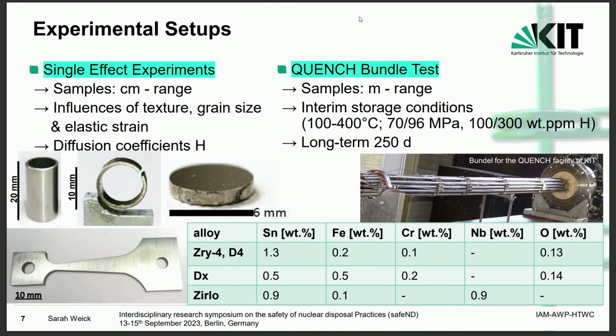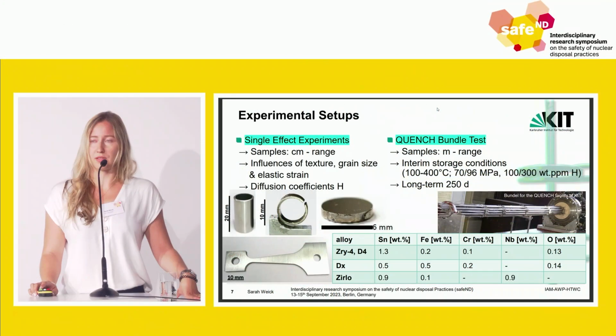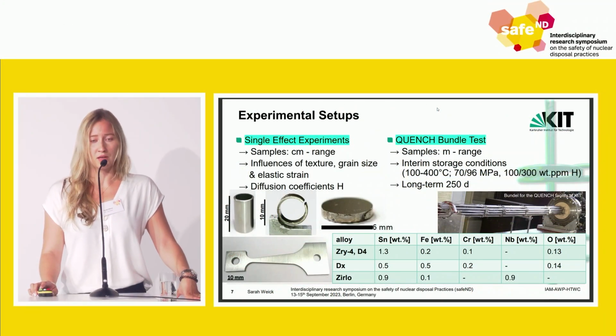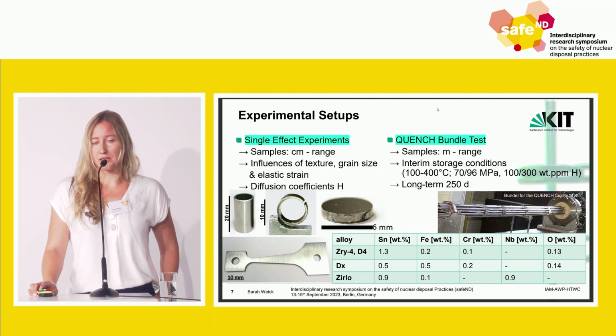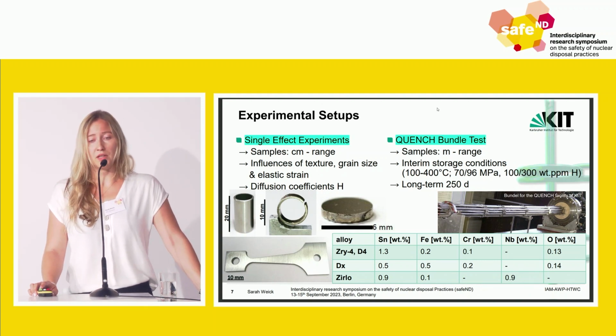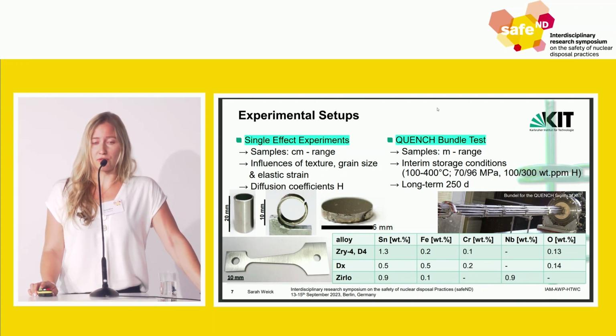For single effect experiments, we generally use original cladding tubes with a height of about 2 centimeters. We also use other zirconium samples, tensile samples, and so on, trying to investigate the influences of texture, grain size, and elastic strain.